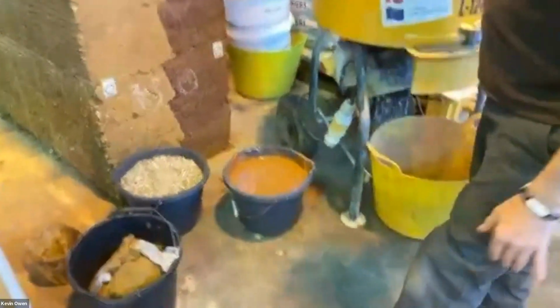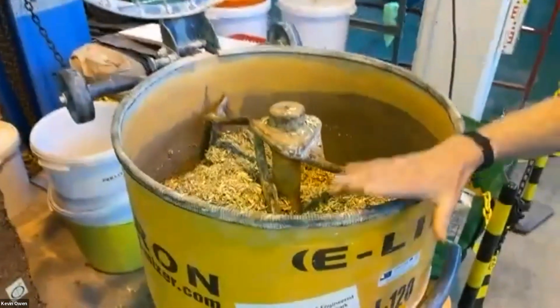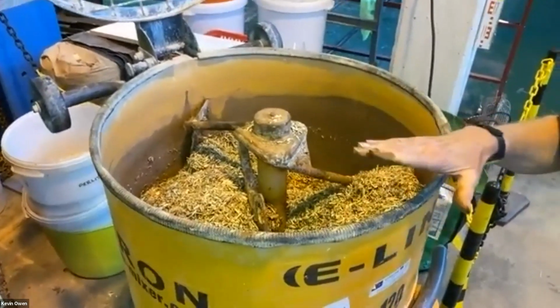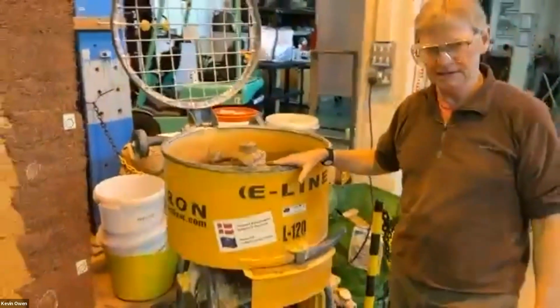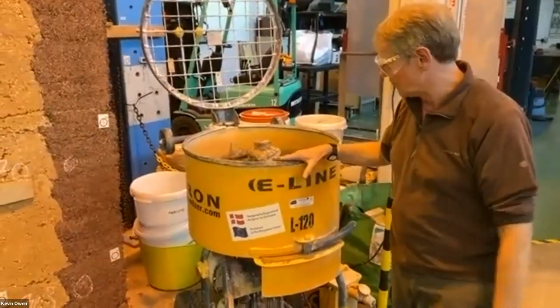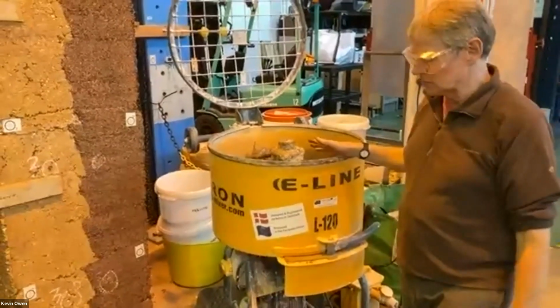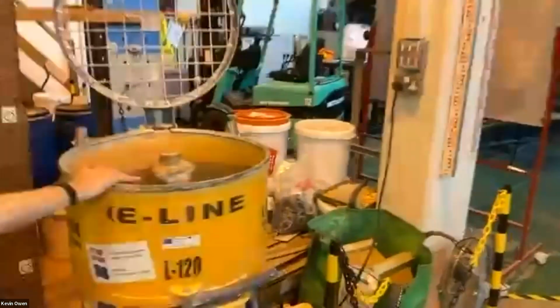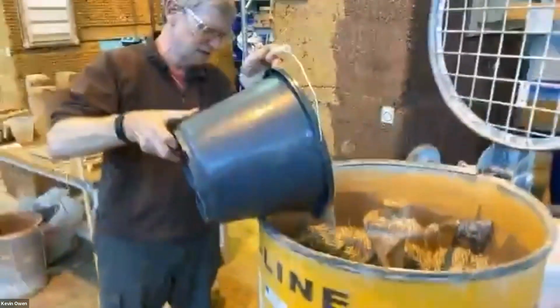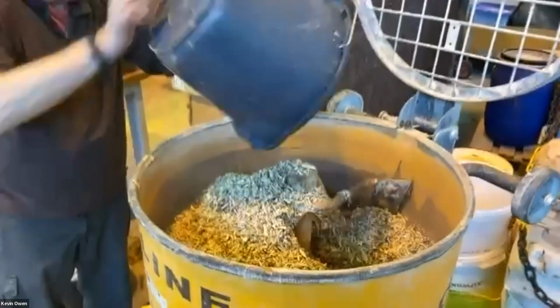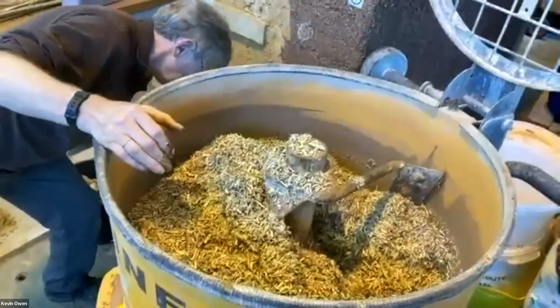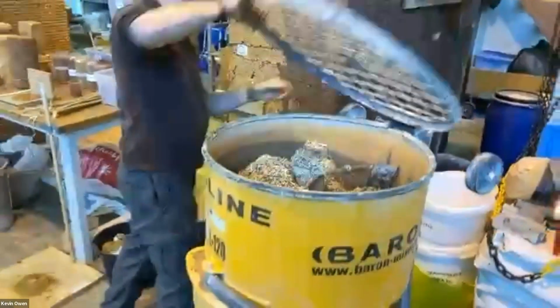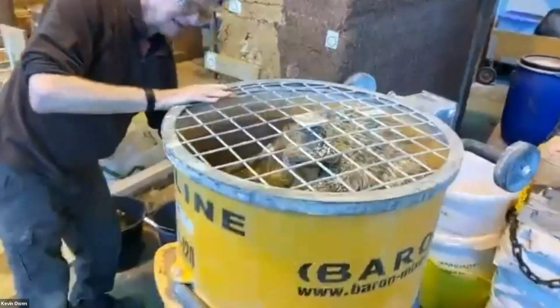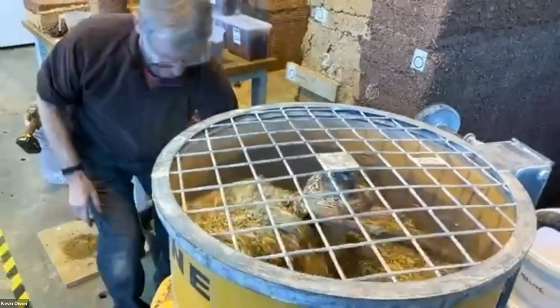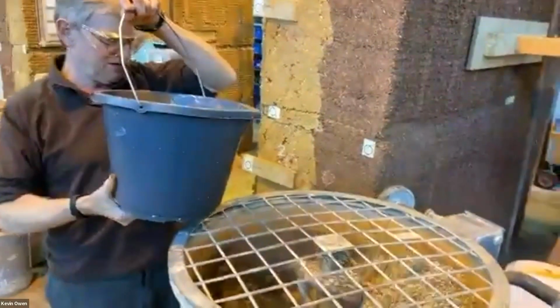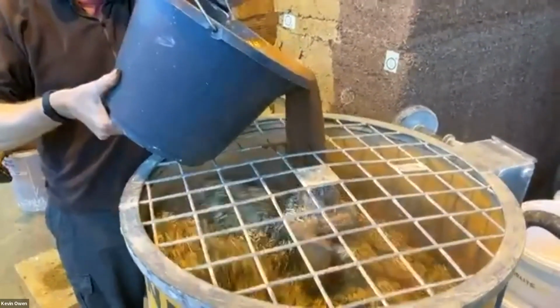Now, what we did on site was we used a vertical mixer like this one. And this actually was used for all our testing and for the building itself. So it's quite a robust machine. It's still working perfectly. I've already put 2 buckets of the material, the shiv, in there. This is my final bucket to go in. And we can start to rotate that. And without pouring it all over myself and John, add in the slip.